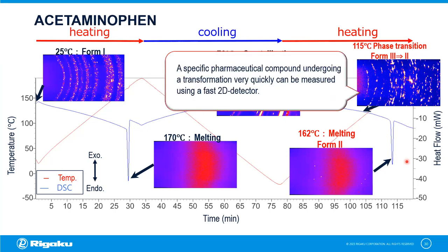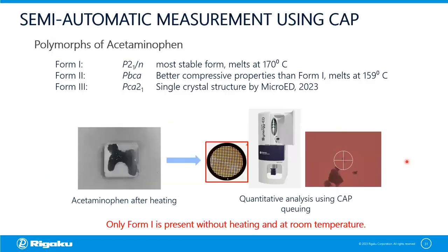So what the XRD-DSC simultaneous experiment allows us to do is to see specific pharmaceutical compounds undergoing transformations very quickly and measured with a fast 2D detector. So I mentioned the crucible. This is an aluminum sample holder, about 5 millimeters by 5 millimeters. We actually use two, one that's empty, one with the sample. That's where the differential in differential scanning calorimetry comes from.